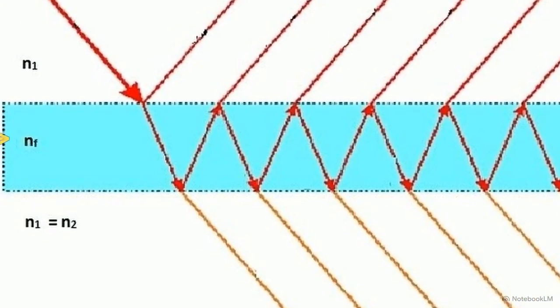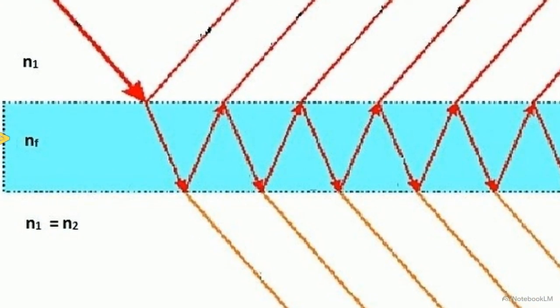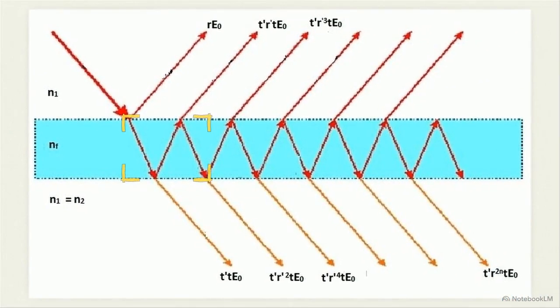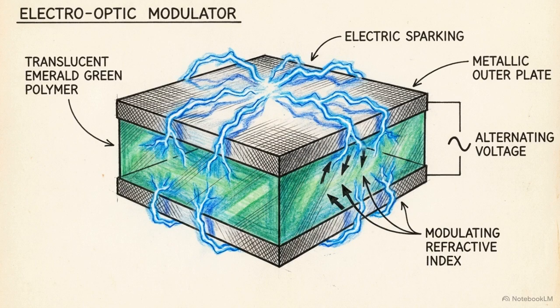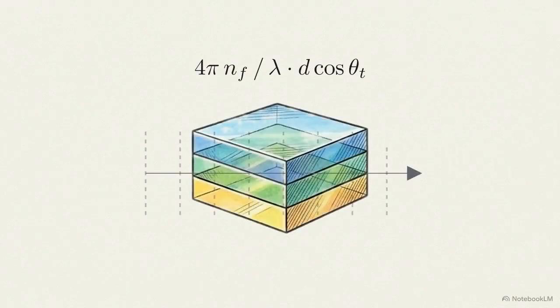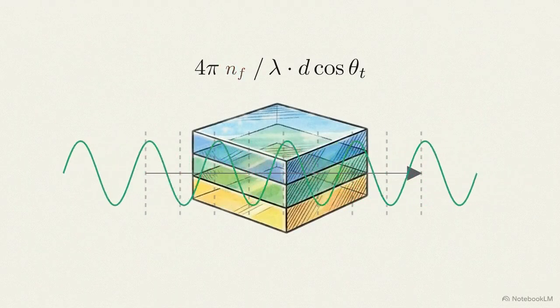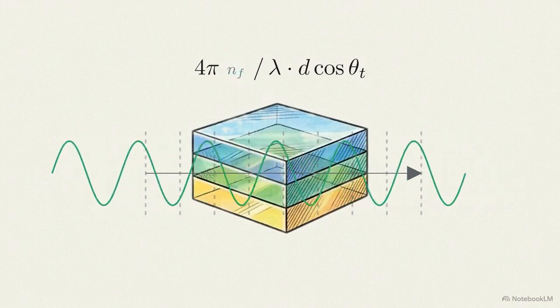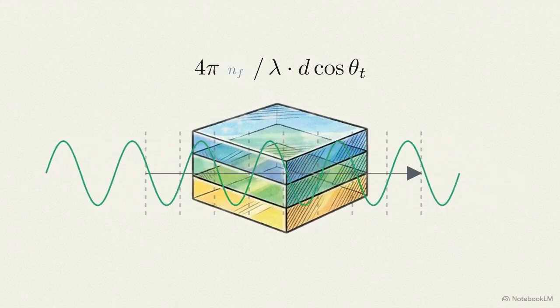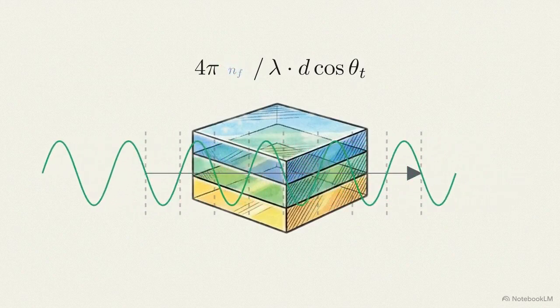The poled polymer is sandwiched between two highly reflective layers of sputtered aluminum. Light entering the polymer bounces between these parallel interfaces, creating multiple transmitted and reflected rays. During testing, an alternating voltage is applied to the aluminum electrodes. Because the polymer is poled, this voltage modulates the material's refractive index. As the index shifts, the optical path length changes. This alters the phase difference of the internally reflected light, directly affecting whether the exiting beams interfere constructively or destructively.